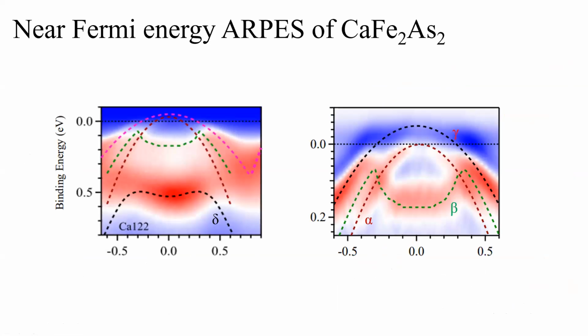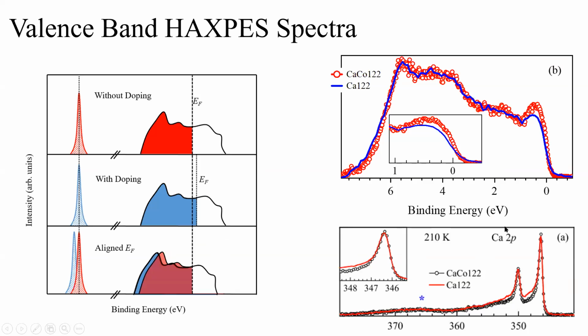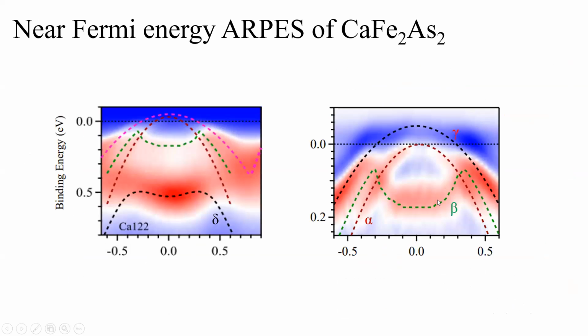So just to understand why we are getting these things here, we looked at the ARPES spectra of this parent compound and the cobalt doped compound. This is the raw spectra, and this one is the double derivative, after a little bit of smoothing. And we can see nicely these three bands. I'm sorry, one band crossing the Fermi energy, one band just going to the Fermi energy, and another band showing this type of feature.